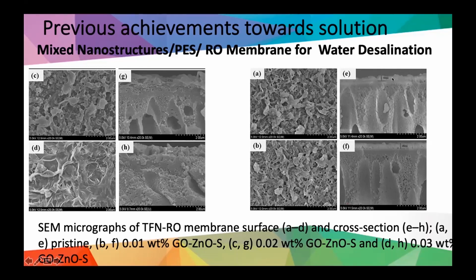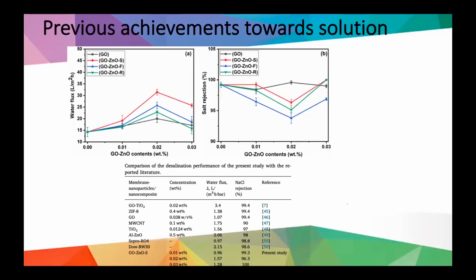Here you can find the active layer, which is changed a lot by the absence of graphene, and then the addition of a certain concentration of graphene oxide and zinc oxide nanospheres and nanorods, which is optimized through this study. The change in the active layer and its structure, as shown in the SEM charts, is clearly shown in the water flux and the percentage rejection, illustrated in these figures.